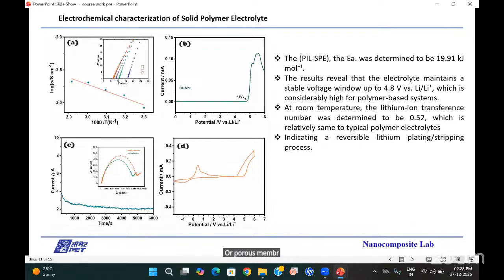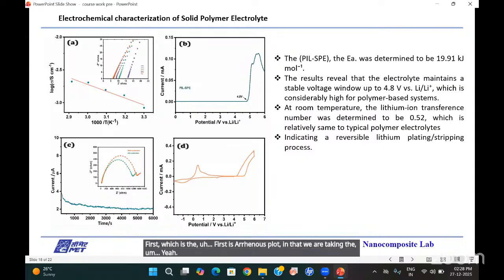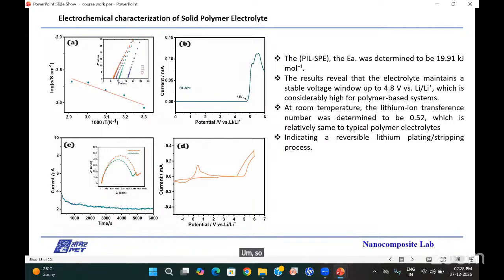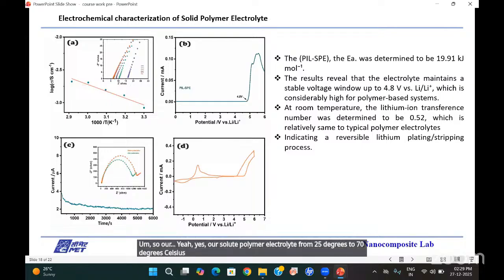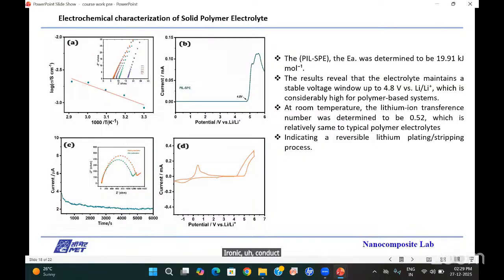Then electrochemical characterization of the solid polymer electrolyte. First is the Arrhenius plot. In that, we are taking the EIS of our solid polymer electrolyte from 25 degrees to 70 degrees Celsius. If temperature increases, ionic conductivity increases, and the activation energy is determined to be 19.91 kilojoules per mole, which is the best.